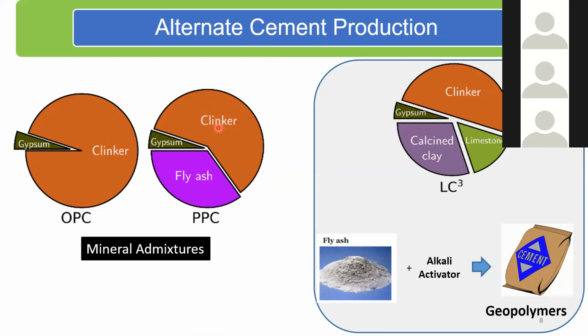We have now come to the point where we are using less and less clinker in our cement, which means, of course, less demand on raw materials, replacing it with more waste materials or post-industrial waste materials, and that has already become the norm. But we're going further, where we're looking at new types of cements called LC3, which basically uses low-grade limestone, and with that, we are able to produce cements with even lower clinker factors. And of course, there is this alternate line of cements we're producing, which are called geopolymers or alkali activated materials, where we start with post-industrial waste materials like fly ash or slag, and we alkali activate them and make cementitious binders out of them, or I should say cement-free binders. And parallelly, technology is developing on those lines to produce concretes of the future.